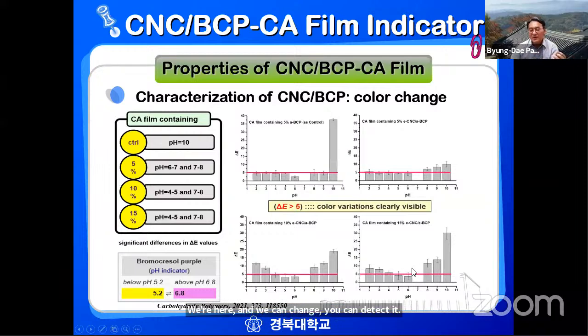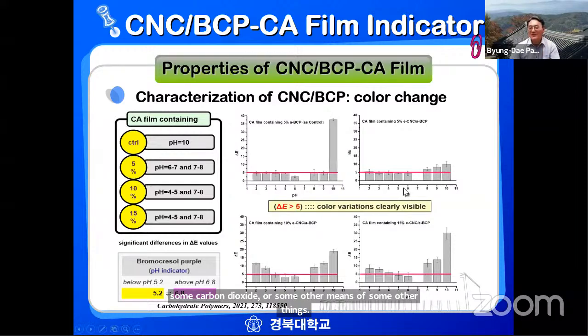And also we have the 15%. There's a little change right here on the left-hand side, the low pH, but here at pH 4 and 5 is a little detectable change, and also pH 7 and 8, above pH 8, we can detect the color changes. So if this film is exposed above pH 8, for example to carbon dioxide or amines or other things that change the color above pH 8, we can detect it with the naked eye.